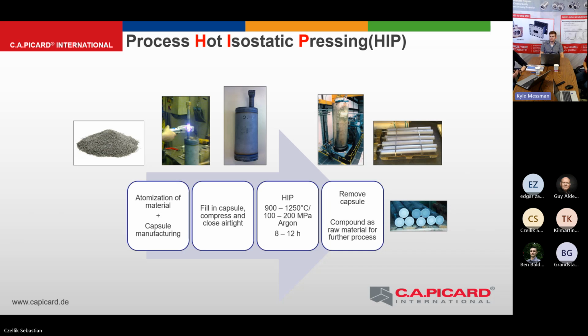When you get this capsule and it's closed and airtight, then you put it into the HIP process. That means we have very high temperatures, a little bit under the melting temperature of the steel, with very high pressures, and it stays there for 8 to 12 hours. When you're ready, you remove the capsule, and then you can work with the material.